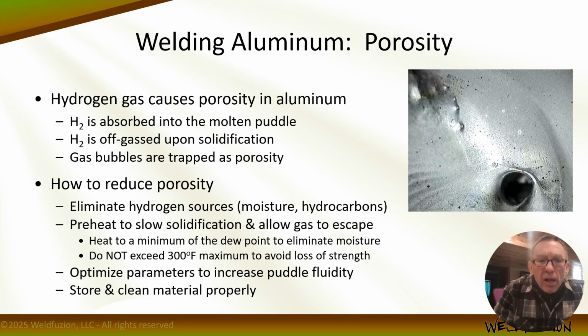Right? Okay. Materials also need to be stored correctly. And I've seen companies actually store aluminum in climate-controlled rooms to reduce the likelihood of porosity, right? Because going from a hot to a cold environment, cold to a hot environment, changes in humidity and dew point, we can all of a sudden see aluminum start to condensate and collect moisture on the surface when we didn't expect it. All right. So, at a minimum, when you're storing aluminum, you don't want to lay that aluminum flat.